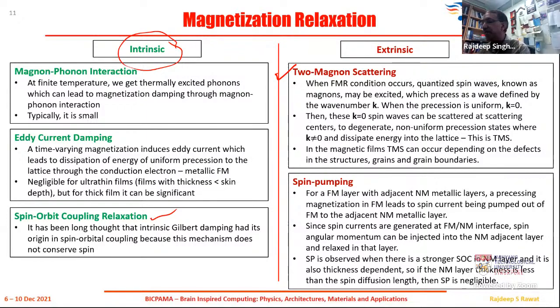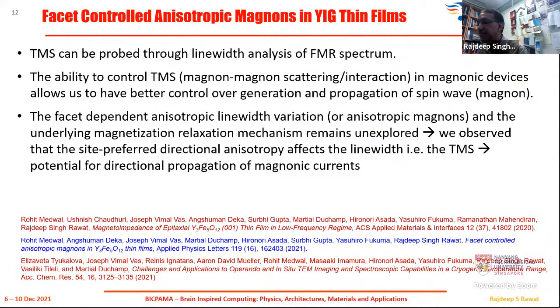This kind of scattering, where the k=0 mode dissipates into k not equal to 0 modes, is what we call two-magnon scattering. And this basically happens when there are defects in the system. Spin pumping I will discuss later on when the time comes. So these are three works that I've listed here related to the YIG work that we have published. But I will concentrate on the second one, which is the facet controlled anisotropic magnons in YIG.